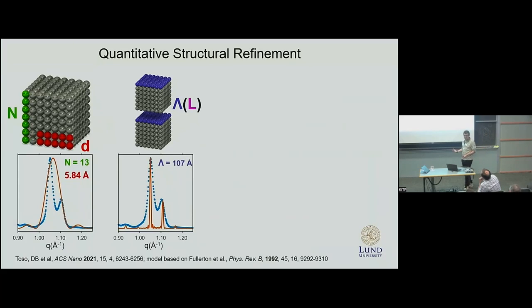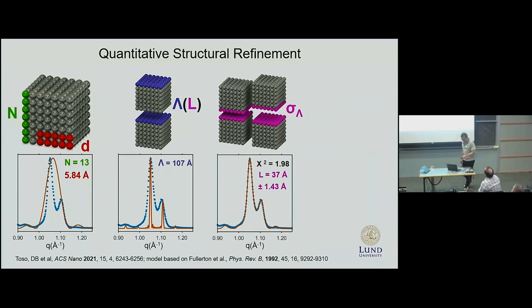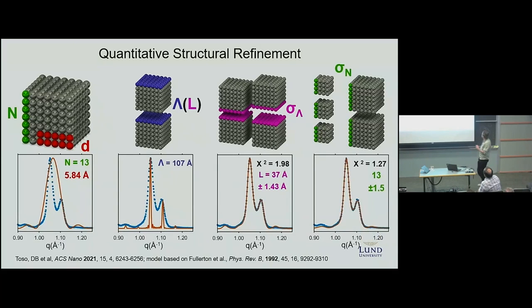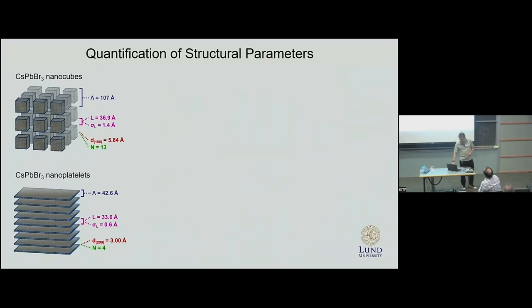There's always some disorder. So next we can add simply Gaussian disorder of this superlattice periodicity, and now we pretty much capture the shape of the experimental diffraction peak. Finally, adding the size distribution, also Gaussian, produces an adequate fit. As a result, we can quantify structural parameters of superlattices, both for nanocubes and nanoplatelets.